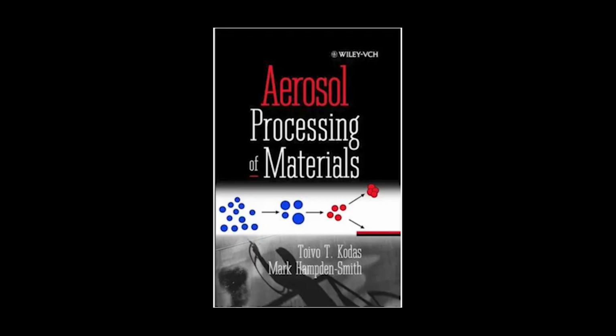Wow. Okay, so we see the reverse of that in droplet evaporation, which is central to liquid-based routes like spray pyrolysis. Right. In spray pyrolysis, you start with a liquid droplet, and you need that solvent to evaporate really fast so the precursor can form a solid particle before it starts to decompose or react. And the timescale here is incredibly short. It has to be. Small droplets, say 0.1 micrometers in diameter, have evaporation lifetimes measured in seconds or even milliseconds. The engineering constraint is this: the evaporation time has to be shorter than the residence time in the reactor before the chemistry kicks in. If it's too slow, you deposit wet, sticky material, which just ruins everything.